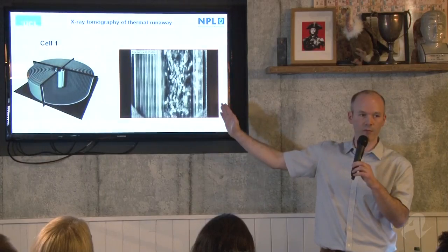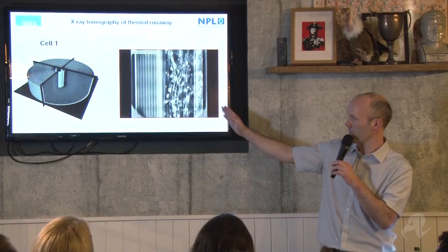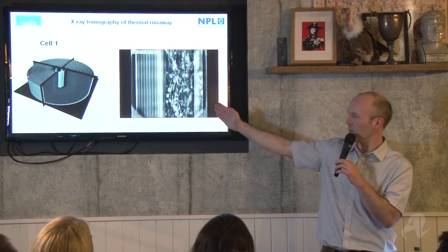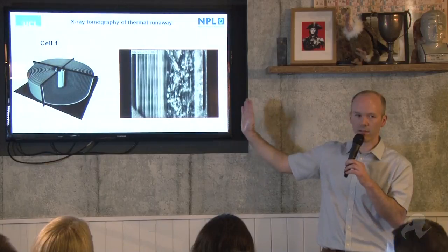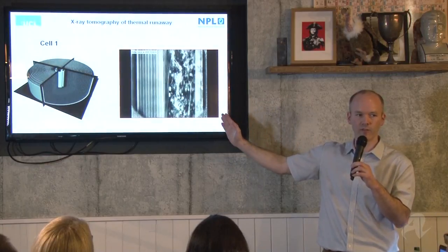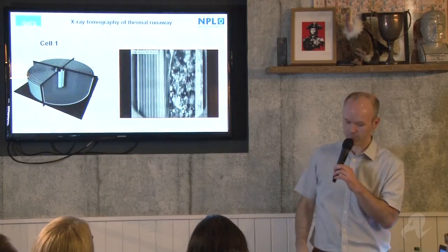What you can see there, those white globules, are actually bits of copper that have melted. The melting point of copper is 1,080 degrees Celsius. And yet, just a few centimeters away, less than a centimeter away, the rest of the cell is undamaged. So there is a huge temperature gradient in that part of the cell. This is the first time anyone had looked inside one of these cells when this process was happening. So this is a very interesting mechanism, and we've used this technique now to look at improving safety features of these types of cells.